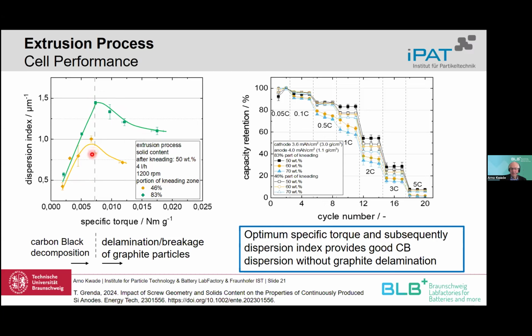And if we now look at the results, you can see that the results with high kneading, but only 83% concentration, give us very good or relatively good performance results. That means a high capacity, even at reasonably high C rates. 1 C means charging the cell in 1 hour.